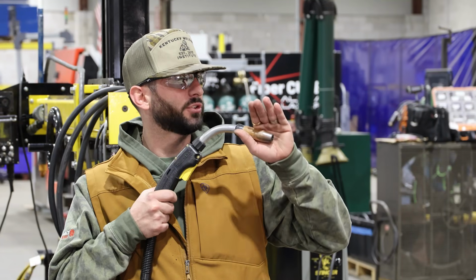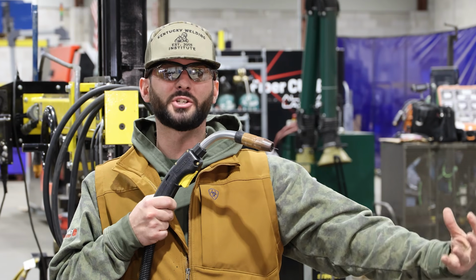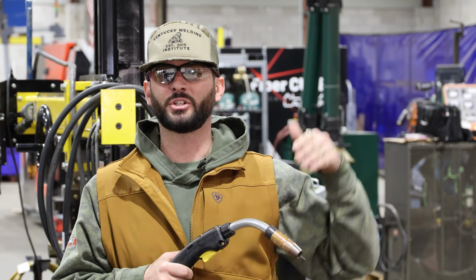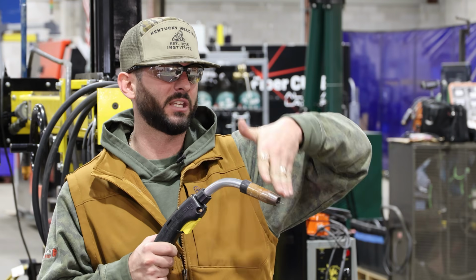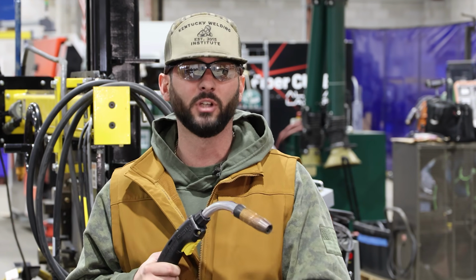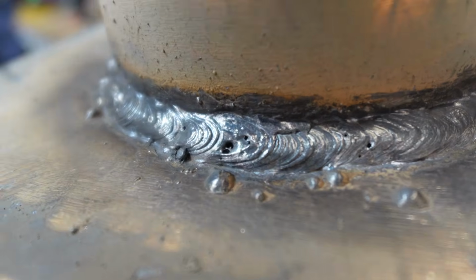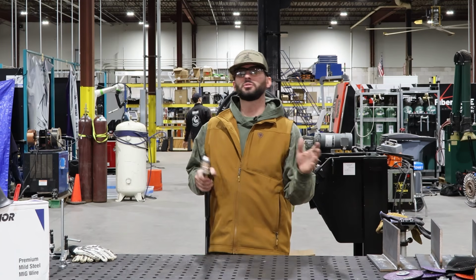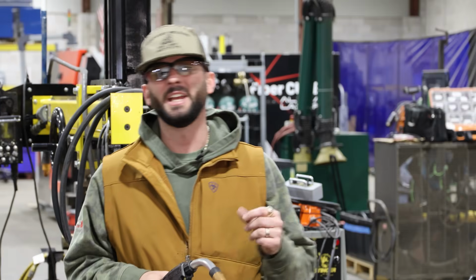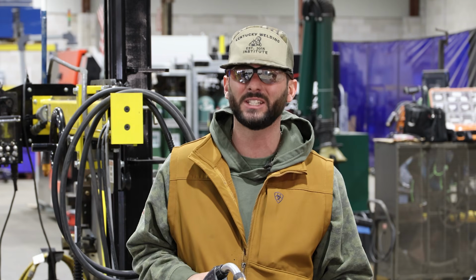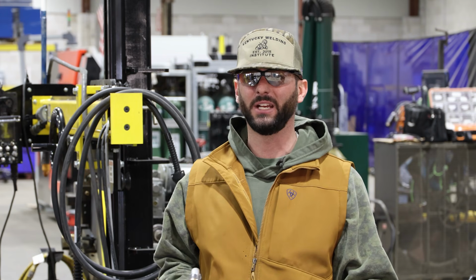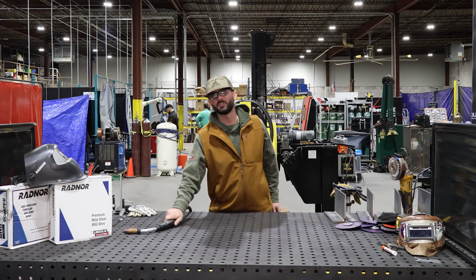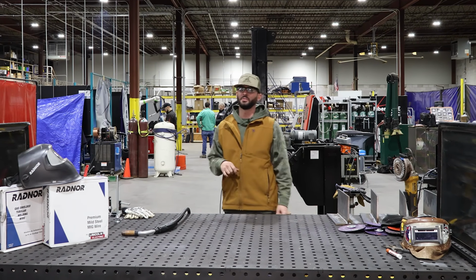Not only that, but when you have so much gas coming out of here, there's pressure being built behind it. We call this the Venturi effect, where other atmospheric gases get pulled in from the back because of the high flow rate. And now you've got a weld with porosity, but you've got gas coming out the wazoo. This usually makes the weld appearance also really rough. And not to mention, you're just wasting more gas than you actually need, so that's costing you money. Now, I'm not going to lie, I've been guilty of turning up my TIG rig to tornado levels and still welding with it. Did I need to have that much shielding gas? Maybe not. Did the weld look extra shiny when I was done? Oh, yeah.